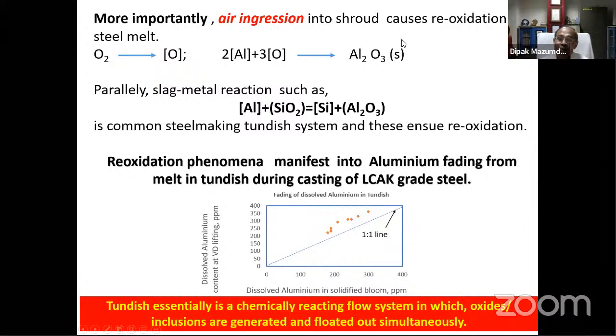And how has dissolved aluminum been removed? It is through formation of alumina. Either of these reactions could take place, as a result of which aluminum can fade and generate non-metallic inclusions, which can jeopardize the steel quality or impair the cleanliness of steel.